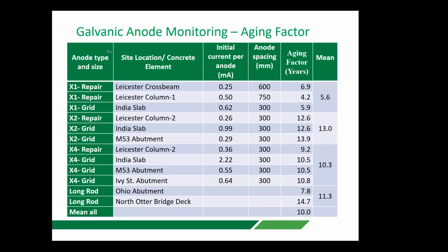Now, since then, we've had a look at about 12 or 13 other situations. This first one is the one that I talked about in detail. We had an aging factor of 6.9 years. The spacing of the anodes, i.e. the distance between the centers of each anode, was 600 millimeters. On an adjacent one, the same place, but in a column, the spacing was 750 millimeters, even wider. And we only achieved an aging factor of just over 4 years in that case.